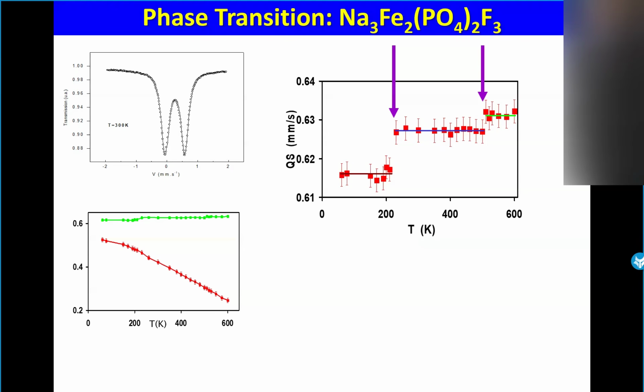We have iron 3+, 3d5, so the contribution is only from the network. If there is a change in the value of the quadrupole splitting, that means there is a change in the structure. To tell the truth, I made the first series of experiments and I was a bit doubtful, so I repeated it to check that there were really two steps. You can see the values of the quadrupolar splitting, 0.62, 0.63, so the error bar is very, very small. You also have to consider that we have a single doublet, so it's very easy to fit.